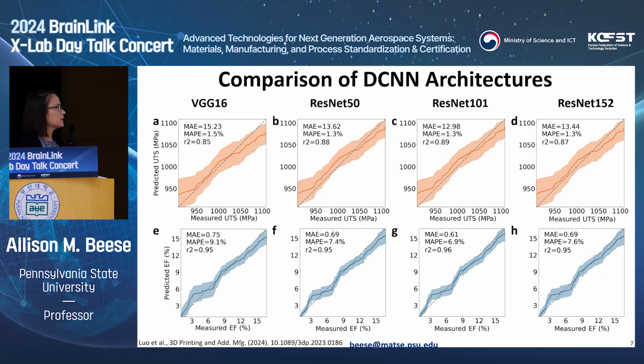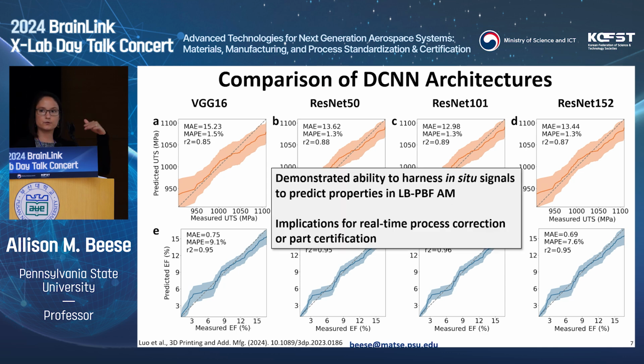And so what we can see here is that we are able to pretty well predict, despite variations in discrete layers, an average strength of our part during processing as well as a ductility. So we could use this then to say we could define a cutoff strength or ductility to say that this is our value, we want to reevaluate the part.